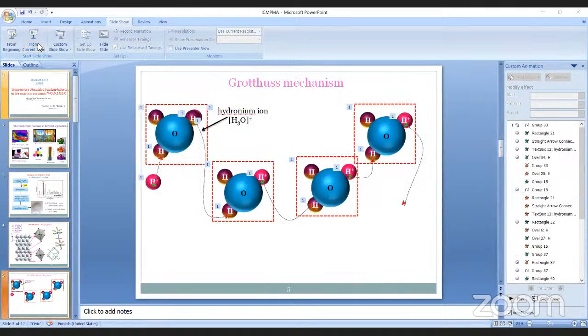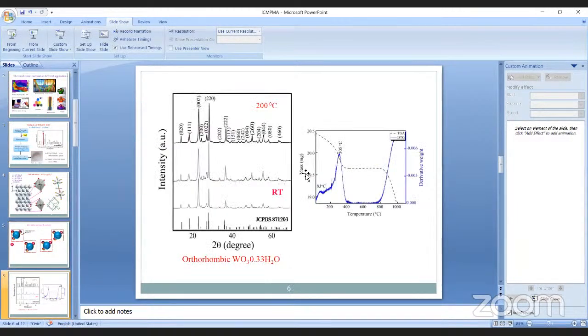Another important property of the water molecule present in the material is the Grotthuss mechanism. In a water molecule, there are 2 hydrogen atoms and an oxygen atom. When we give the temperature stimulus, one of the H plus ions gets liberated and moves towards another water molecule. For a small fraction of a second, a hydronium ion is formed. Then this knocks out another hydrogen ion for conduction, and thus proton hopping occurs, giving the Grotthuss mechanism to the material. The sample is annealed to different temperatures, and the TGA measurements show that when the sample is annealed up to 300 degrees Celsius, the material remains in its hydrated form due to its intercalated water content.